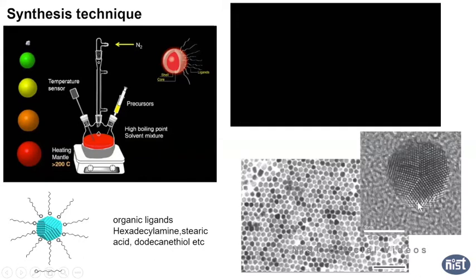It's very highly crystalline, and you can see the atoms very well. The white part is the void, and the black part is the atoms, so it's a high resolution TEM image. The scale bar is 5 nanometers, so you can see the atoms very well. That's why, as I told you earlier, it's called an artificial atom. It's a slightly bigger nanocrystal, but the number of atoms is not so much. It's maybe 10,000 atoms, and so that's like that.